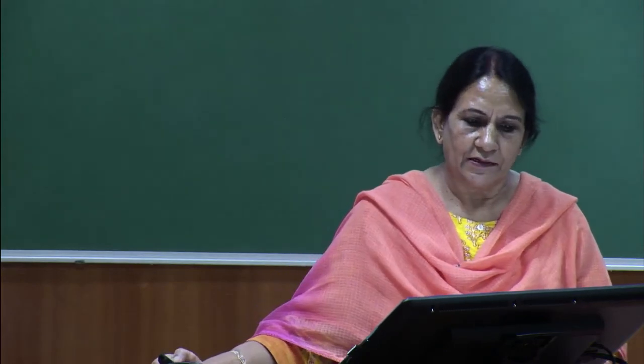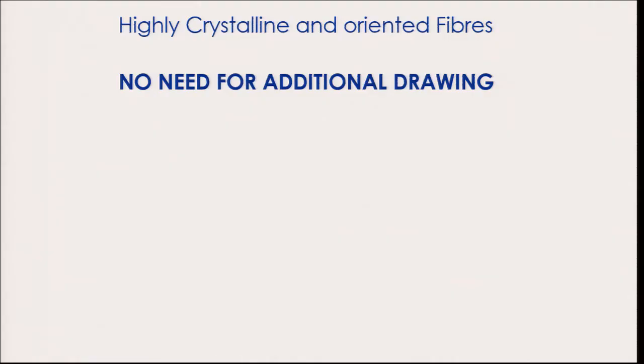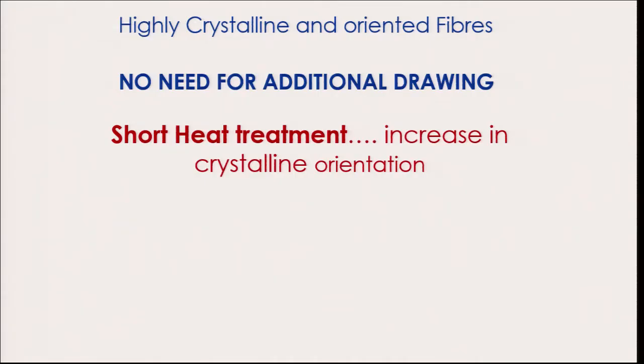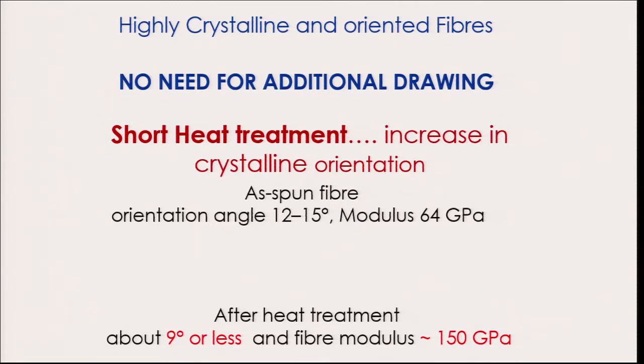So, what I would like to say is the highly crystalline and oriented fibers which are obtained in this case, they do not need any additional drawing. We do not need to carry out any additional drawing in the case of these fibers. However, a very short heat treatment in tension can result in an increase in the crystalline orientation. So, very often these fibers, as-spun fibers, are given a short heat treatment,